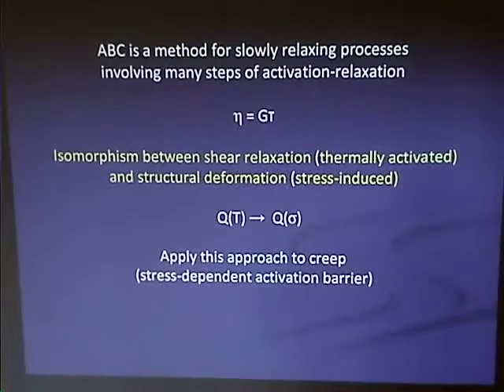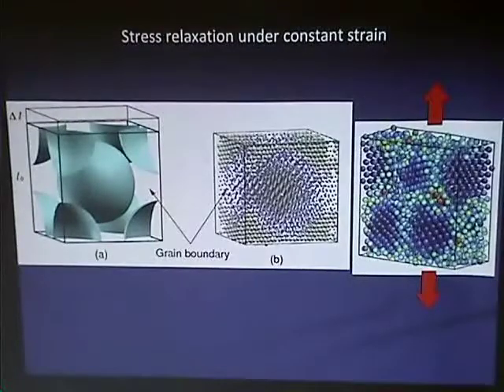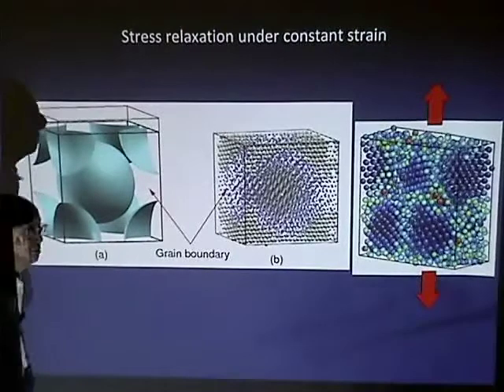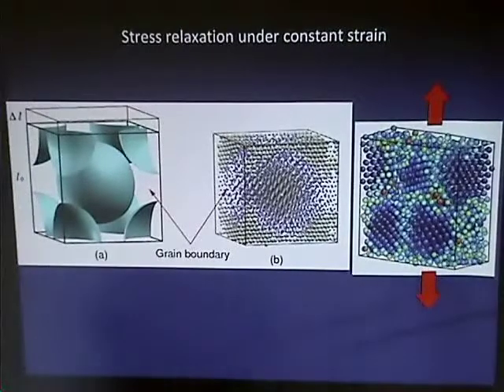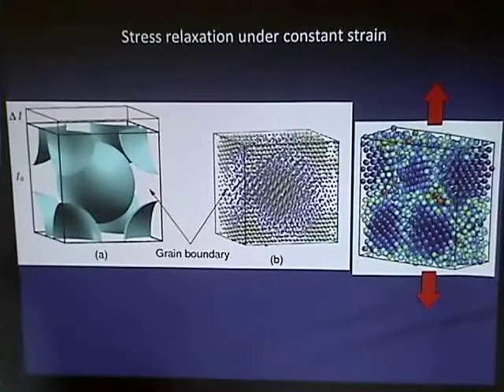Usually it's thought to involve mass transport. Particles actually move from one side of the grain to another, so the grains elongate and eventually the system elongates. We can do this, and the experimental counterpart is that people for years do internal friction measurements. They look at a crystalline sample and either put a stress on it or a strain on it. Imagine you stretch your system a percent or so and just wait and wait.